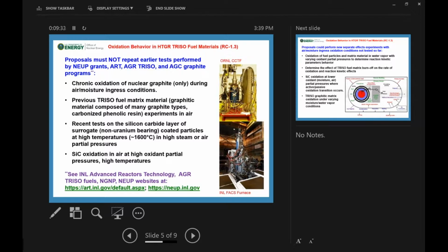We've had recent tests where we've had very small flat plates of non-uranium bearing material, and we've done some high temperature, high steam or air partial pressures. That has been done at Oak Ridge. So please be careful not to just put in for that only. If you need to do some of those tests just to check your equipment, that will be fine, but we can use those results we already have as benchmarks. And again, oxidation in air at high oxidant partial pressures and high temperatures have been done. We would like you to do it specifically in the 1,000 to 1,600 degrees Celsius in the transition range.